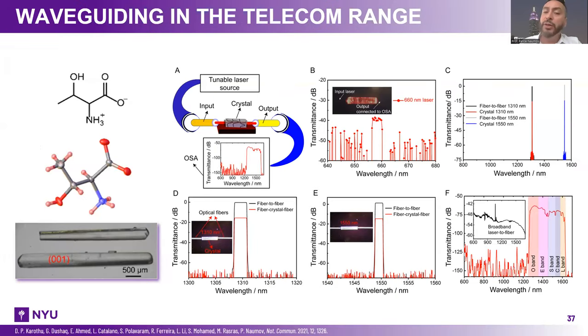But I have to remind you here that the signal that we receive over internet or waveguides, they don't come in the visible part of the spectrum. Actually, they come in the near infrared part of the spectrum. As you can see here from the spectrum, we have these different bands and all the information comes in this part of the spectrum. So we ask ourselves, can we replicate this with organic crystals? Yes, we have to have a very small molecule which has a very strong transmission in that part of the spectrum. And indeed, this is a simple amino acid where we can actually use the crystal of this amino acid to transfer near infrared pulses or signals and then collect it from the other side. So this is the first demonstration that we can use organic crystals as optical transducers in the telecommunication regime.